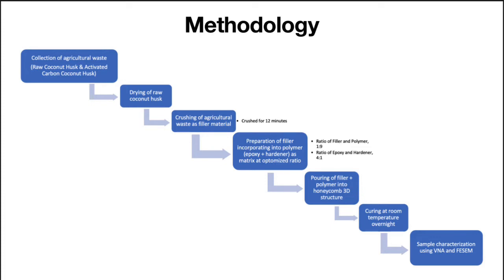The crushing process involves the filler material, which is the raw coconut husk, for it to be in powder form. Note that in this research, we use commercially obtained activated carbon coconut husk in powder form. Next, we mix the filler incorporated into matrix in a beaker by using a glass rod. After reviewing various sources, we decided to use epoxy and hardener as the matrix with ratio of 4:1, while for the ratio of filler and polymer matrix, we use 1:9.